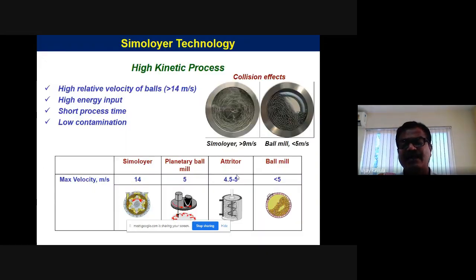The reason is because it generates a very high kinetic velocity, greater than 14 meters per second. And that's why the energy input, half mv square, is very huge. Then there is the short process time and low contamination, because milling is a very dirty process. If you keep milling, there is a lot of wear and tear on the balls and vials, and the longer the duration of the milling, the higher the chances of contamination of the powder by the ball material or the vial material. Typical high energy ball mills like the planetary mill give you only 5 meters per second, an attritor gives you 4, and conventional ball mills give you less than 5 meters per second, whereas this horizontal ball mill gives you 14 meters per second.